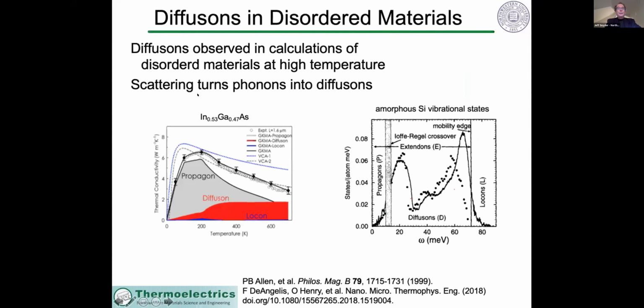So diffusons have been found mostly computationally, originally by looking at amorphous materials, but more recently, diffuson type transport can be found even in crystalline materials with disorder. So this is a disordered crystalline material where, particularly at high temperature, the diffuson contribution can be very large and even dominate.